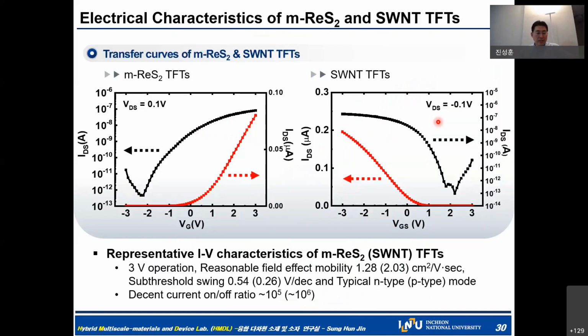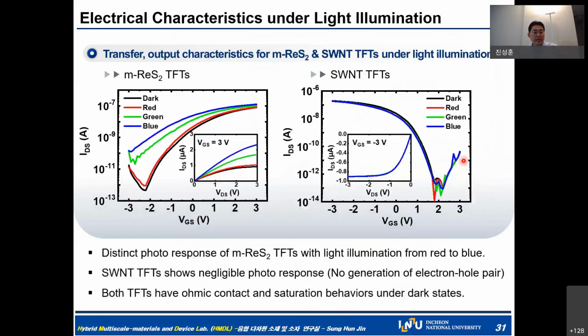But typically, we achieve a very wonderful N-type, the m-ReS2 transistor, and on the right side, the carbon nanotube transistor has achieved the P-type property. Interestingly, as expected before, for the m-ReS2 we observed very high photodetectivity across different wavelengths. However, for the carbon nanotube, the sensitivity to light is fully negligible.